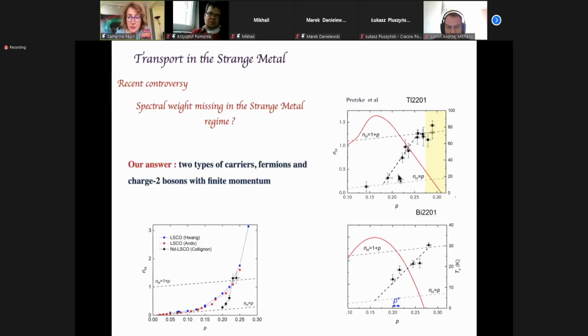So they go with the group of Nigel Hussey that the number of carriers goes from small hole pockets here, like p, to a big Fermi surface over there. So the same data, but the interpretation differs, they don't completely agree. They agree on the data, which is already something for the two groups, but they don't agree in the interpretation.